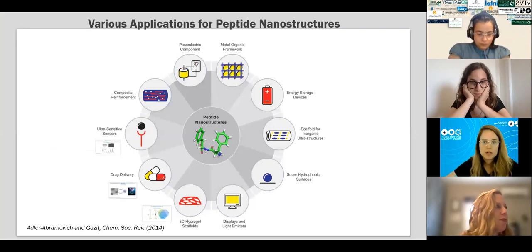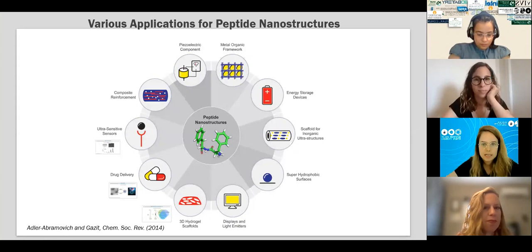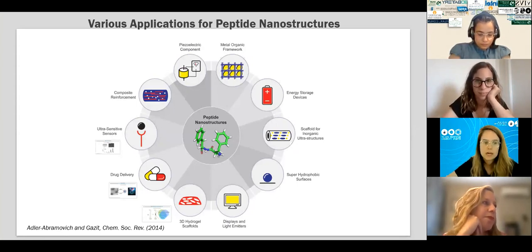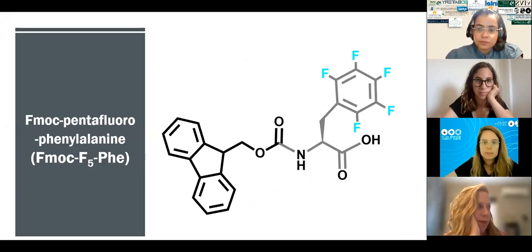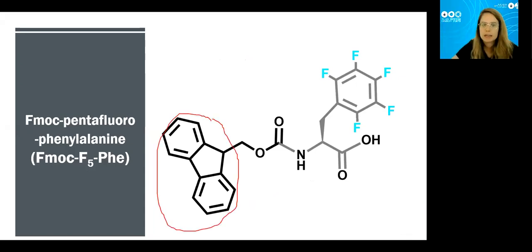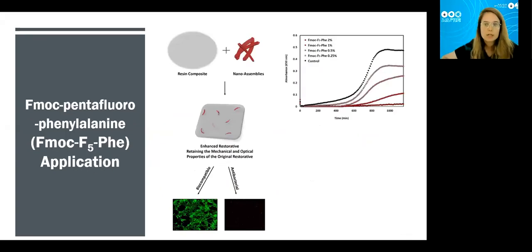Self-assembly has many applications including ultra-sensitive sensors, drug delivery, and in our lab we are also investigating 3D hydrogel scaffolds for tissue engineering. My research explores the self-assembly of Fmoc-pentafluorophenylalanine, a modified amino acid based on the Fmoc group. This building block is well studied; recently our lab demonstrated its antibacterial activity against Streptococcus mutans for dental medicine applications. We incorporated the nanostructure into a composite material showing antibacterial properties while maintaining biocompatibility and optical properties — importantly the tooth did not change color.